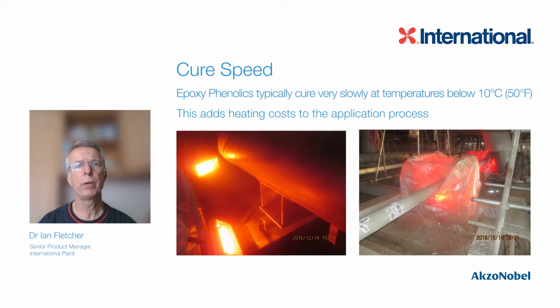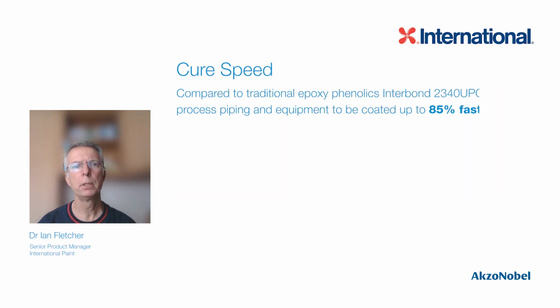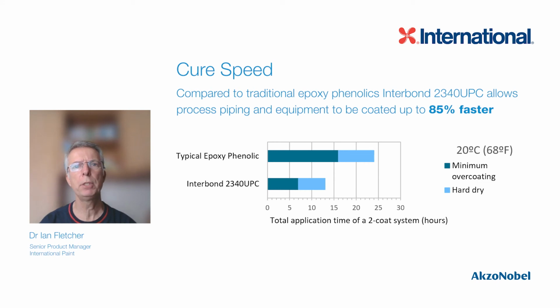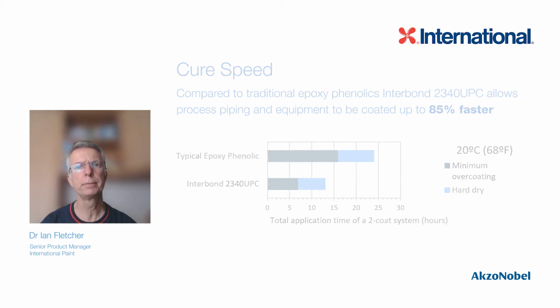Epoxy phenolics typically cure very slowly at temperatures below 10 degrees Celsius, and this can add heating costs to the application process, such as the use of heat lamps. Conversely, 2340 UPC can be used down to -5 degrees Celsius, being hard dry in 10 hours at this temperature. 2340 UPC has faster hard dry times and has much shorter overcoating times than traditional epoxy phenolics. This means that compared to traditional epoxy phenolics, Interbond 2340 UPC allows process piping and equipment to be coated up to 85% faster, which greatly improves pipe shop productivity.